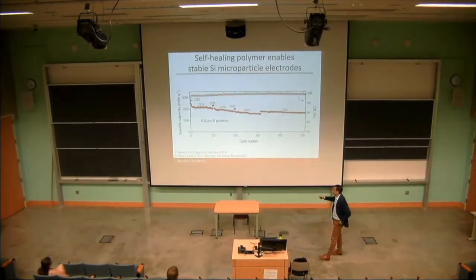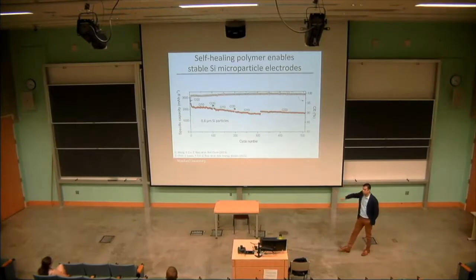So here's, if you're not used to looking at these plots, this is specific capacity. So this is how many electrons we were able to put in per weight of silicon versus cycle life. So we just charge it up and discharge it and see how much we get out. And then the C numbers are just different rates. So C over a smaller number is faster, C over a bigger number is slower.